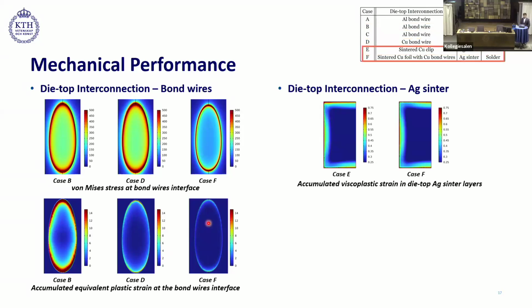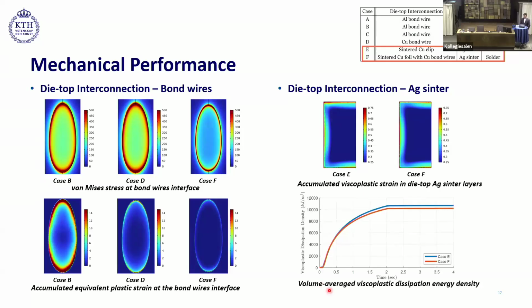Now, looking at the die top interconnection silver sinter, here we see the viscoplastic strain accumulation in die top silver sinter layers. And if we focus on this region, then we observe that in case of copper clip, the die top silver sinter accumulated a bit higher viscoplastic strain than what we used in case of copper foil. Looking at the volume averaged viscoplastic dissipation energy density, we see that it is a bit higher in case E with copper clip than case F with copper foil. So from this study, we concluded that the kind of material we are using inside the package and also the kind of configurations that we have in the module, the thermal and the mechanical performance both can vary.